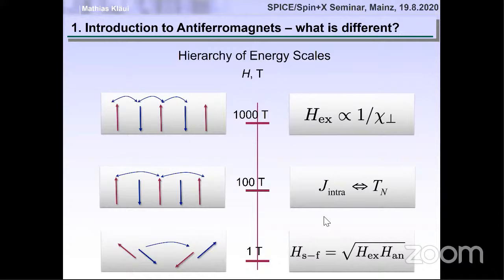I think that I made myself quite clear, and I just mentioned that in my first comment, that as a general statement, that this Néel temperature is determined by intra-sublattice interaction in general is not true, because it may be true for frustrated systems. And I made this remark that if it's not frustrated, this is not true. It's simply nearest neighbor inter-sublattice coupling. That's what determines Néel temperature and sublattice magnetization. Maybe in a particular system you consider like nickel oxide, that's more tricky, but it's frustrated. It's FCC. So as a general statement, that's simply not true.